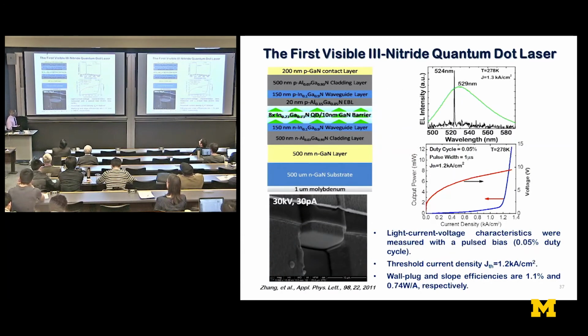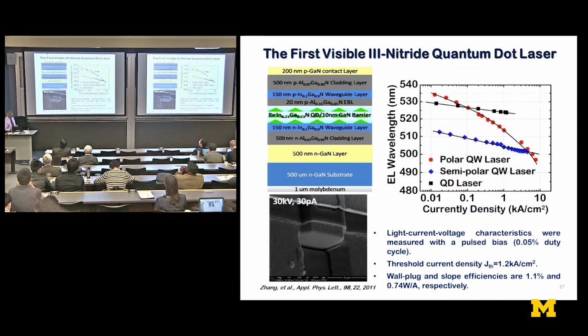And so, to make a long story short, we made the first quantum dot laser in the nitride system, which lased at the green wavelength, and then followed it. And you can see, we measured the polarization field, and you can see the blue shift with current density is much, much smaller than even semipolar quantum well lasers, these were being made at Nakamura-san's company, Soraa.